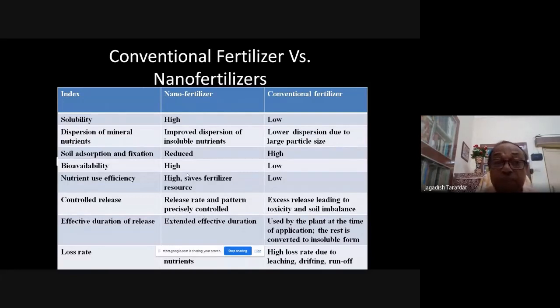Actually, if you look at chemical fertilizer, the duration of release is only 3 to 10 days. But if you go for nanofertilizer, the release rate extends to 30 to 40 days. So that way you can have an extended duration of release and you can minimize the losses of nutrient.